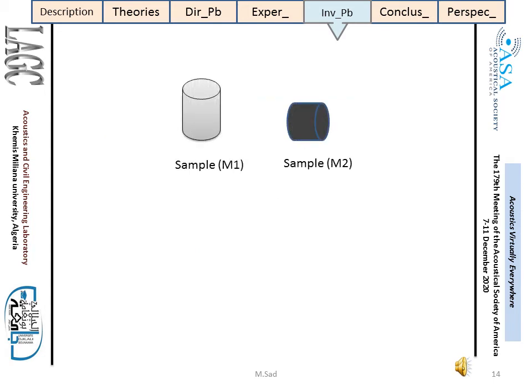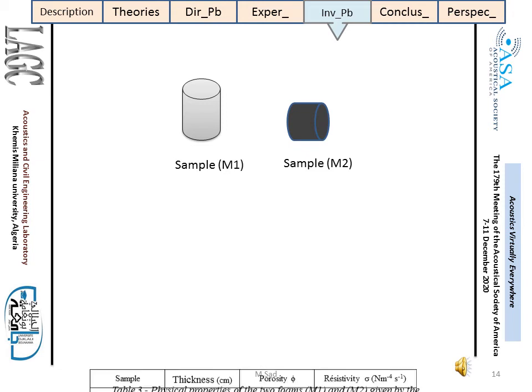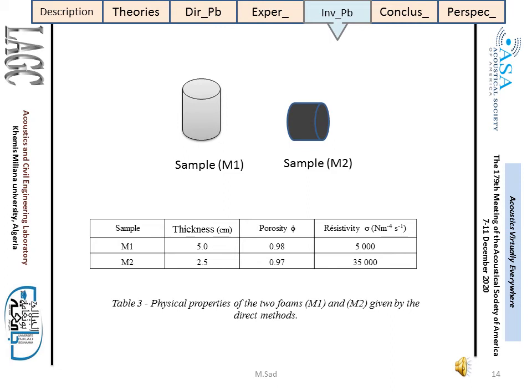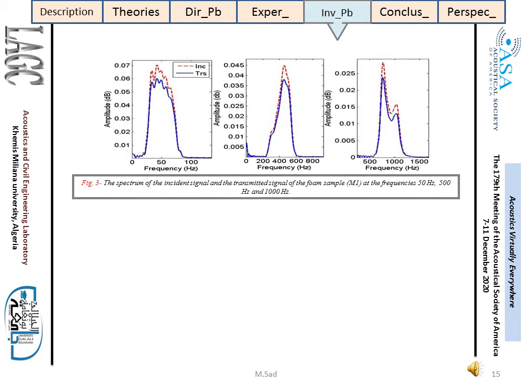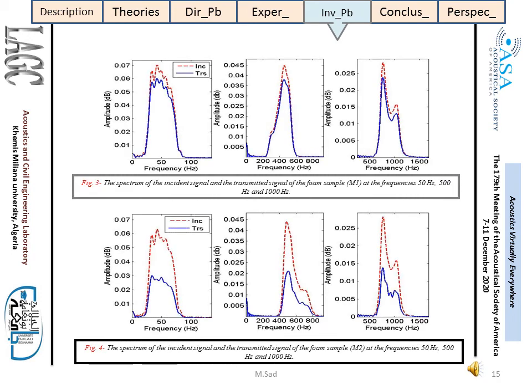The two study samples are industrial plastic foams M1 and M2 of thickness L1 equal to 5 cm and L2 equal to 2.5 cm. The physical properties of these two foams measured by direct methods are given in Table 3. Figures 3 and 4 show the spectrum of the incident signals and the experimental transmitted signals of the two foams at frequencies 50 Hz, 500 Hz, and 1000 Hz.